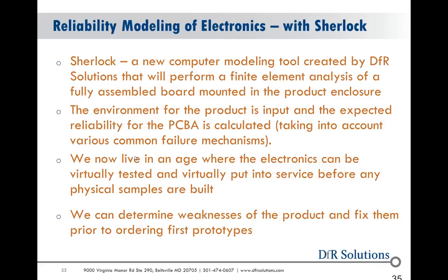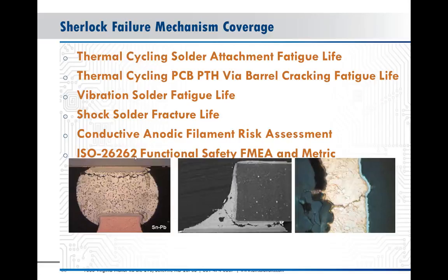You can have a good understanding of how that product is going to perform in shipping, storage, and field use before you've built anything, and therefore you can make design changes early. The failure mechanisms it covers include things like thermal cycling of solder joints — you can thermal cycle the product virtually and tell which solder joints are going to fail and when. Plated-through-hole failures like barrel cracking can also be predicted as you get expansion of a board during thermal cycling.